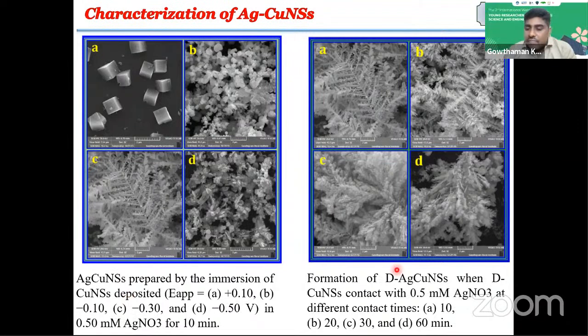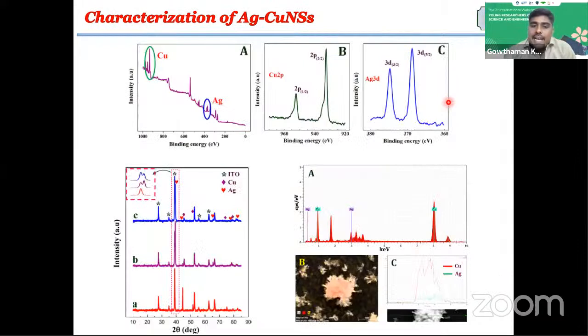Also, at different timing, only 20-minute immersion time gives the plentiful and fruitful formation of Ag copper bimetallic nanostructures. So within 20 minutes, we can form the bimetallic nanostructures on the electrode surface. So it can be characterized by